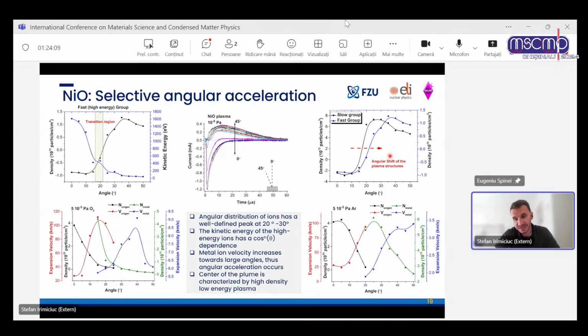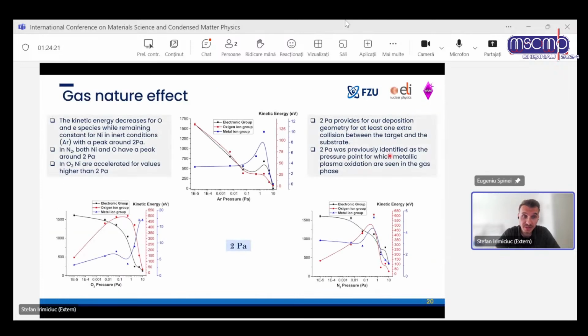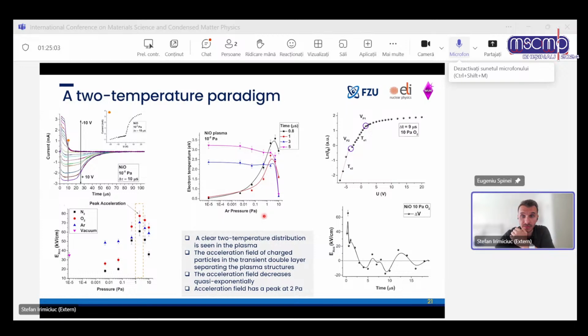So the point of all of this is that we have a really complicated deposition system, complicated even for simple elements. For nickel oxide, we can get nice films, but we can also understand why. For the gas phase reaction, if we're looking at argon, nitrogen, or oxygen for the nickel oxide, the only relevant effect is on the oxygen part, where we can see for the metal ions energy the acceleration. So if we put more oxygen in the nickel oxide system, it will not slow down the plasma, as happens with argon and nitrogen. It will accelerate, and that will affect the properties of the film. This is something that we know, and we can control further with this.